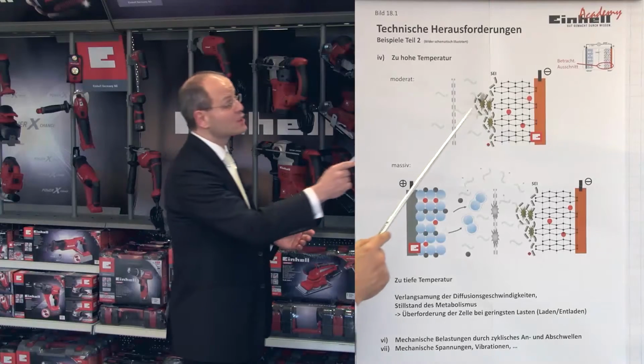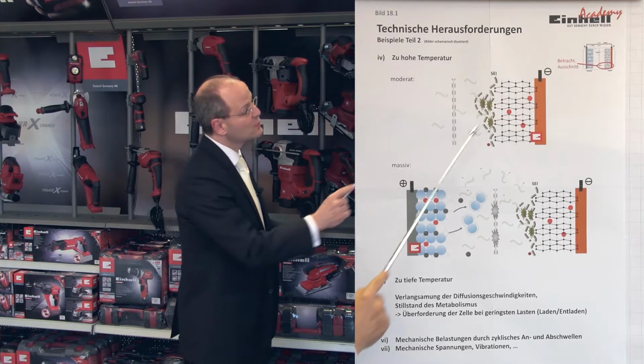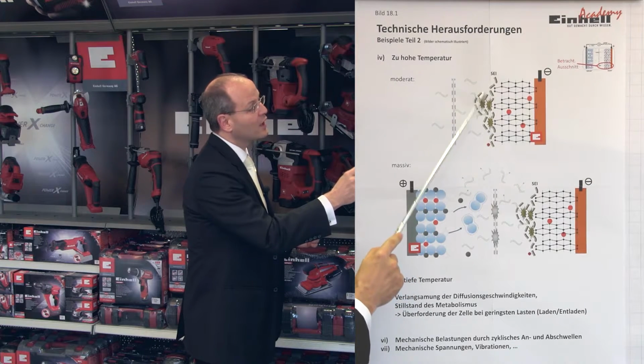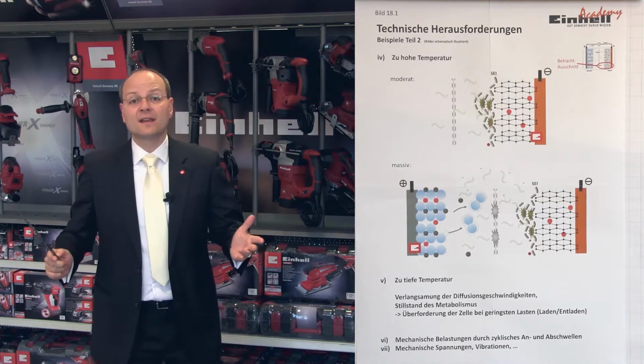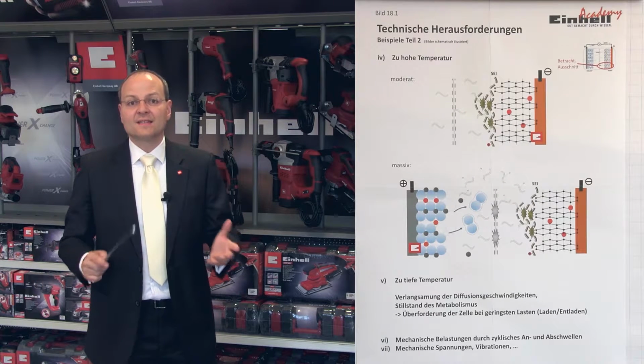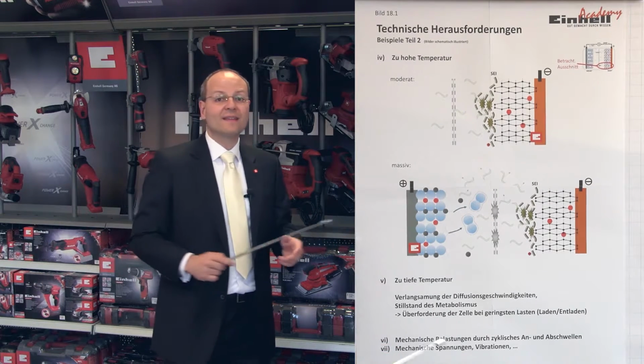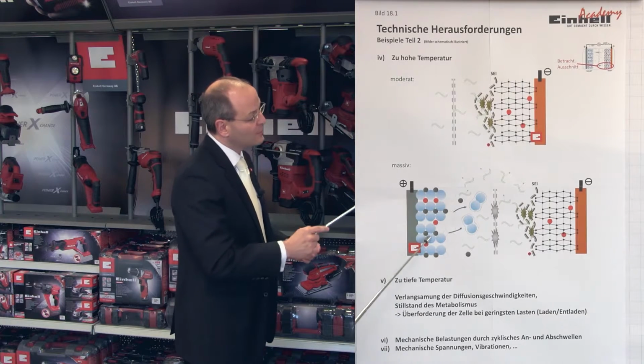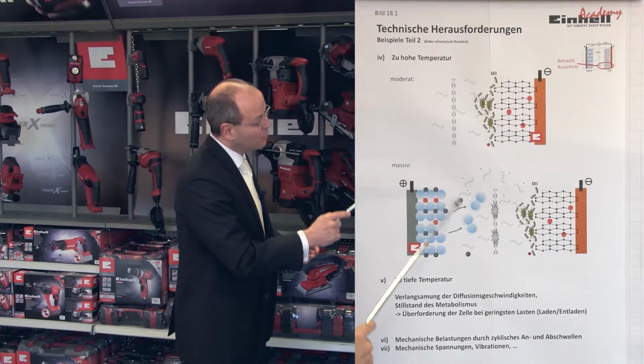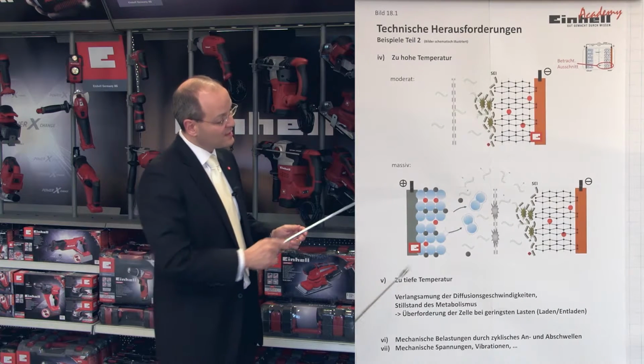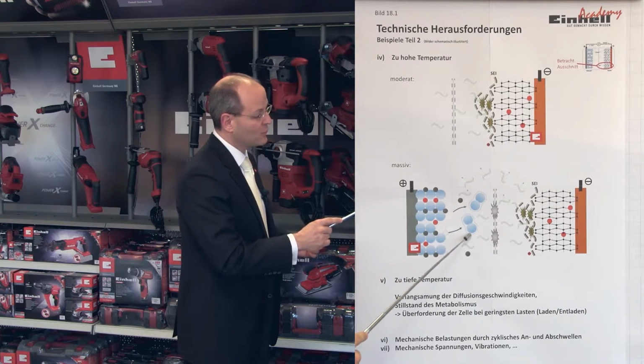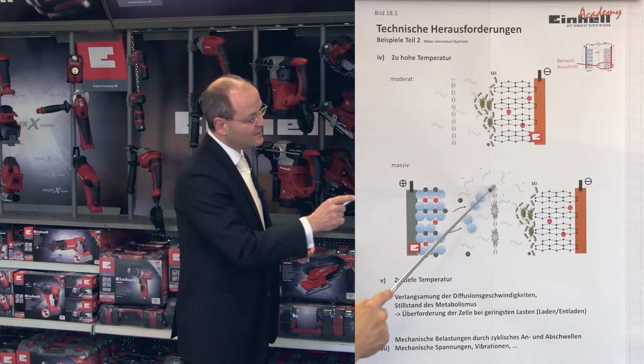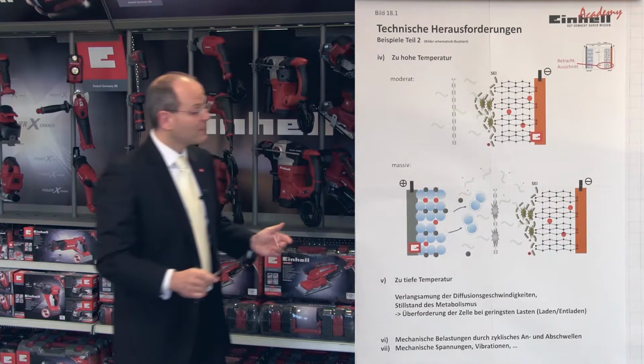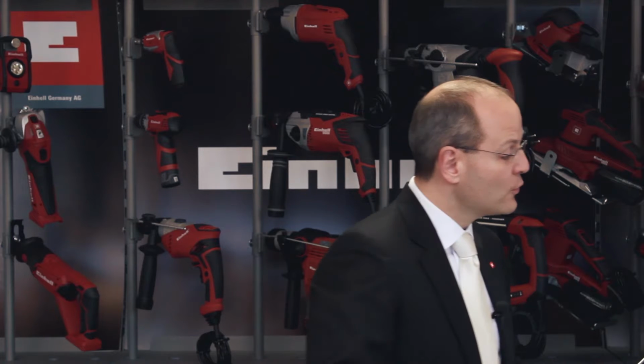If temperatures are too high or too low, this can also destroy the cell. For example, under excessively high temperatures, the SEI will be destroyed. It is immediately recreated in a reaction between carbon and the electrolyte. Unfortunately, this is an exothermic reaction, which means that heat is released in the process, thereby raising the temperature even further. At higher temperatures, the cathode, which is highly sensitive to high temperatures, decomposes under formation of oxygen. In addition, the separator can also be damaged in the process. Low temperatures slow down the speed of diffusion and the metabolic rate in the cell.